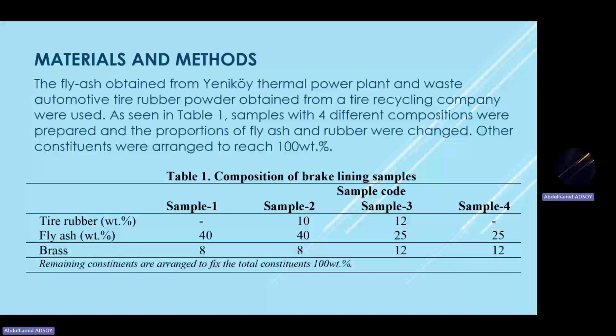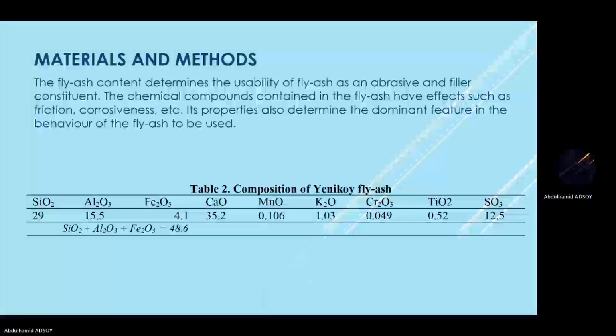Now, the fly ash content, also the chemical composition of the fly ash itself, has significant effects on the properties of the brake lining composites. So, as you can see from this table too, we have the chemical analysis of the Yeniköy fly ash. SiO2 is at 29%, alumina has 15.5%, and iron oxides have 4.1%.